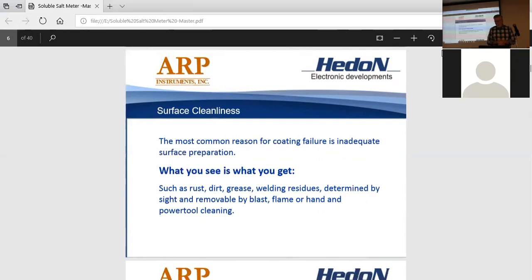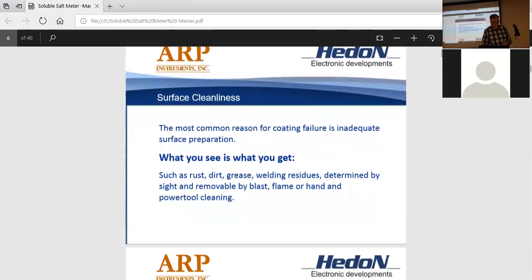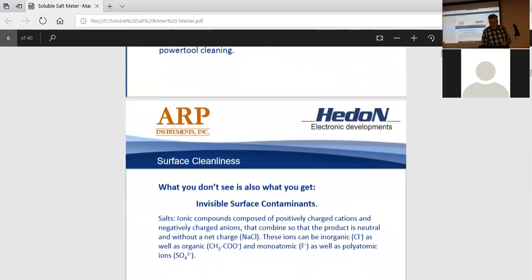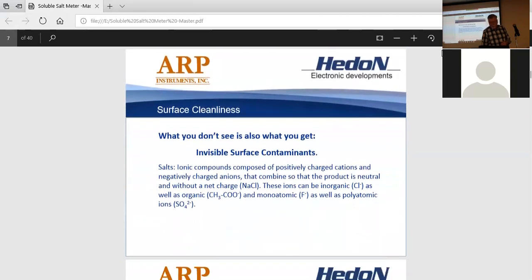So if you obviously compromise in rust and grease and weld spatter residues, you can remove those things by blasting for some time. You can do heat, flames, surface tools. But what I tell you is that what you can't see is what you get: the surface contamination left behind. Even if it's a white metal surface prep, soluble salts are still there. They're not visible. And these soluble salts are mostly sodium chloride ions. That's the biggest killer. But there's other materials. There's sulfates, nitrates, and other materials.